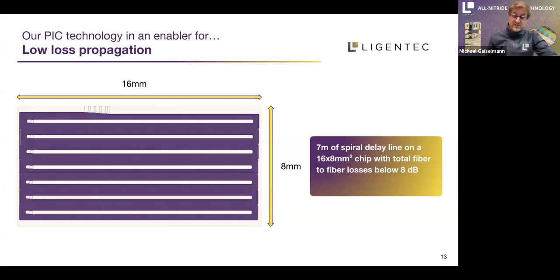And when you have such a very low loss propagation platform, actually it's amazing what you can do with it. You can put a 7 meter spiral delay line on a 16 by 8 square millimeter chip. So that's a chip that is smaller than your fingertip, and you have a 7 meter delay in nitride waveguide with a fiber to fiber loss that can reach below 8 dB, including coupling of the fiber to the chip and the propagation loss in the circuit. And that is only possible because we combine very low loss with a relatively high confinement of the mode, and can, like this, get a very compact chip size